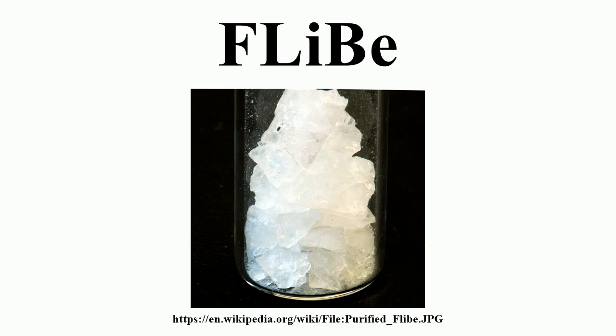excessive corrosion. The easiest method to prevent undesirable reactions is to pick materials whose reaction voltages are far from the redox potential of the salt in the salt's worst case. Some of these materials are tungsten, carbon, molybdenum, platinum, iridium, and nickel. Of all these materials, only two are affordable and weldable: nickel and molybdenum. These two elements were chosen as the main portion of Hastelloy N, the material of the MSRE.